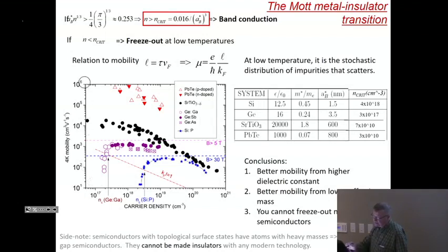So here, for example, is the mobility of semiconductors as a function of carrier concentration. And we're going to be working at low temperature. And so you can take germanium. Where's germanium? Germanium's here. You can take germanium and dope it progressively less and less, and then at this n-crit, which is here, the conduction falls, the mobility falls. Notice that this condition, which is this one, this is the Joffe-Regel limit, Kf times mean free path is 1. These are two different conditions. It turns out they very often coincide more or less, but not quite.